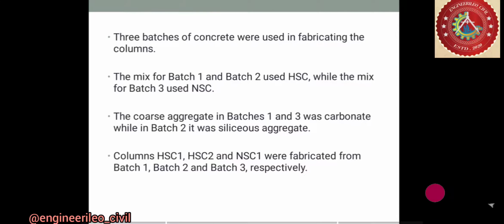The coarse aggregate in batch 1 and batch 3 was carbonate, while in batch 2 it was silicate. And here in this table you can see the batch mix properties: mix 1, mix 2, mix 3, with cement content, fine aggregate, coarse aggregate, water cement ratio, and admixtures like silica fume and superplasticizers. And now we are going to see the test apparatus.